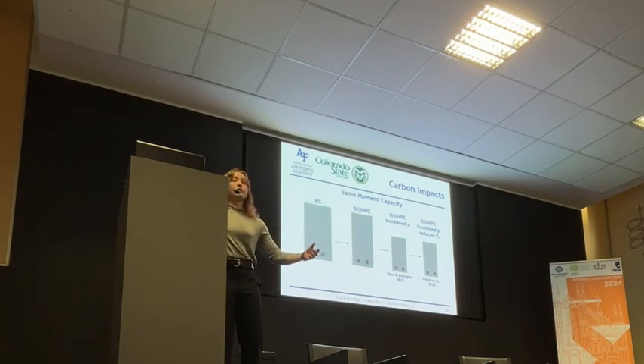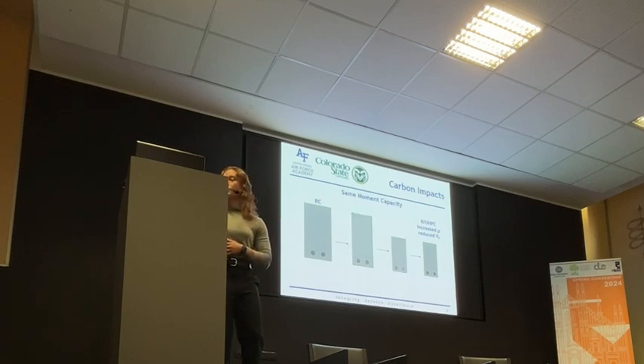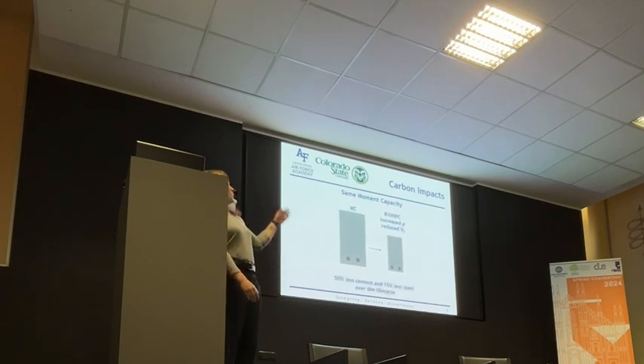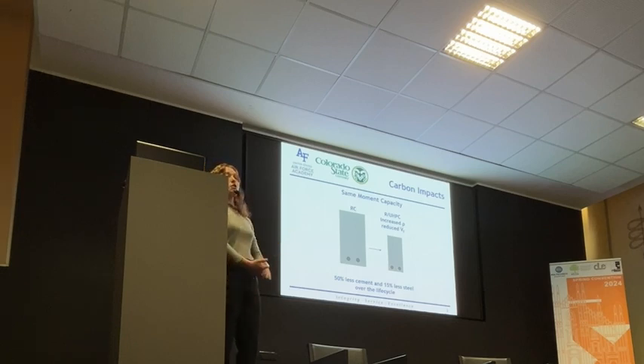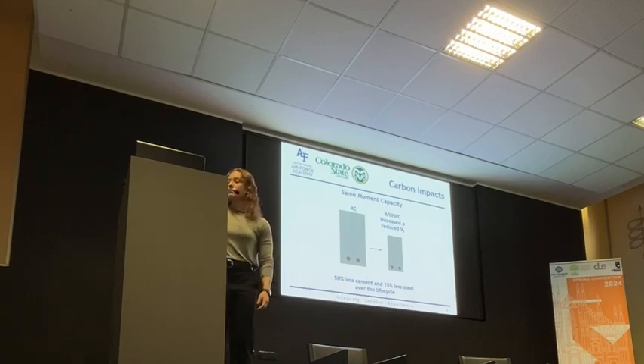And then from our own previous research that we've done, we have even found that you can reduce the volume of fibers within the cement from 1 to 3%, which is typically used in industry, to 0.5% of steel fibers, and it still performs well under compression and tension, and still prevents spalling. So as you can see from this transition, you take a giant cross section of normal concrete, transition it with the efficiencies that we have found with our research and looking at the literature review. You can make a UHPC specimen much smaller in size while still maintaining the same moment capacity. So it's a very impressive material, and this just shows how you can take advantage of the material properties and the lifespan of this material.